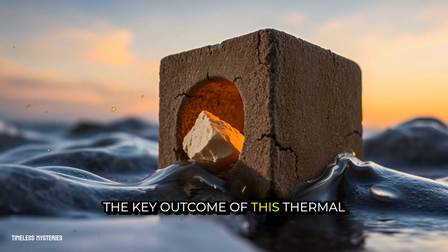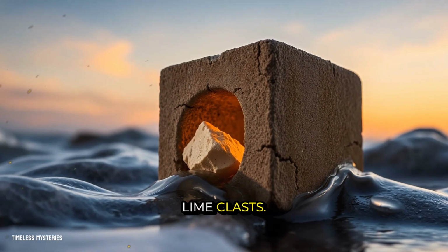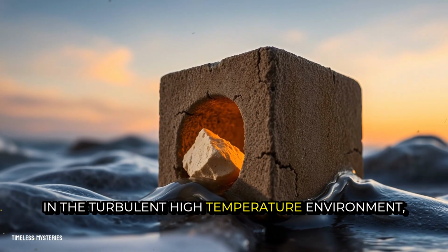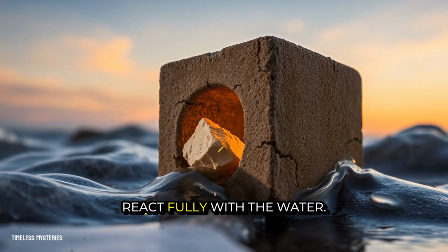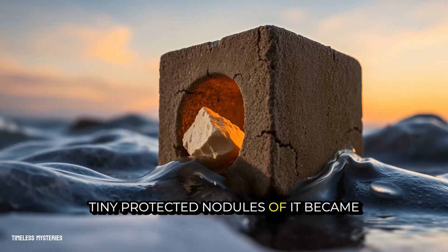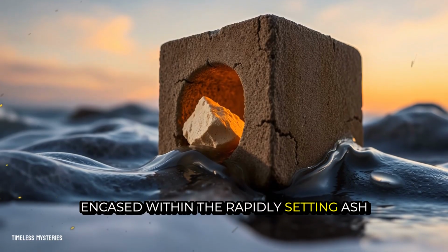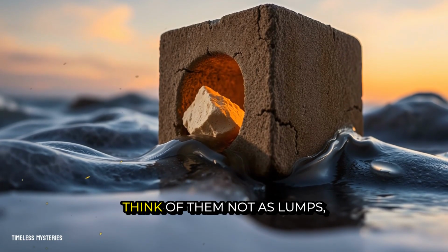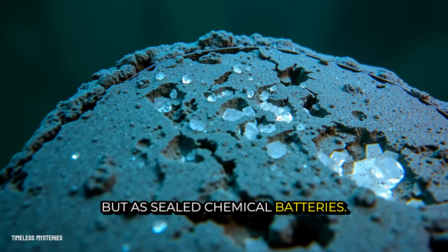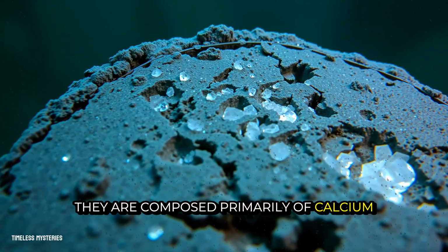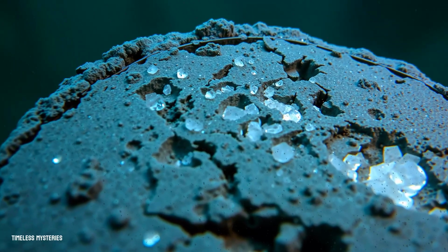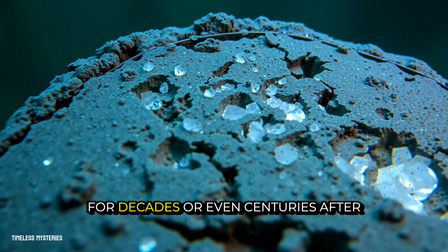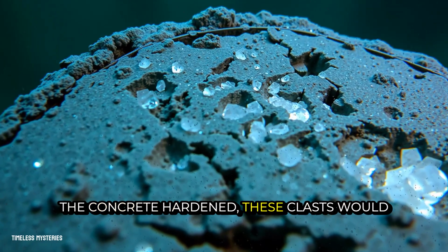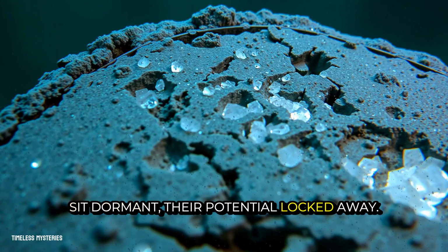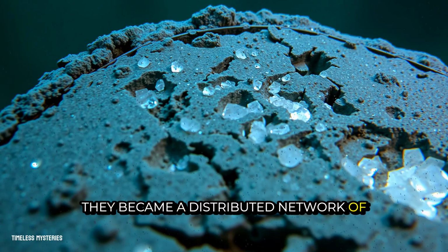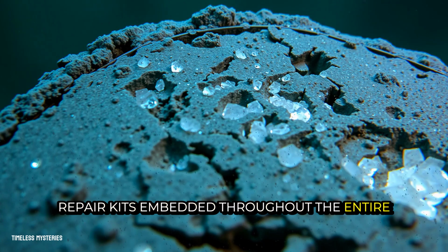The key outcome of this thermal chaos was the creation of those lime clasts. In the turbulent, high-temperature environment, not all of the quicklime could react fully with the water. Tiny, protected nodules of it became encased within the rapidly setting ash and aggregate matrix. Think of them not as lumps but as sealed chemical batteries. They are composed primarily of calcium oxide, a substance with a powerful, latent desire to react. For decades or even centuries after the concrete hardened, these clasts would sit dormant, their potential locked away. They became a distributed network of repair kits, embedded throughout the entire structure.